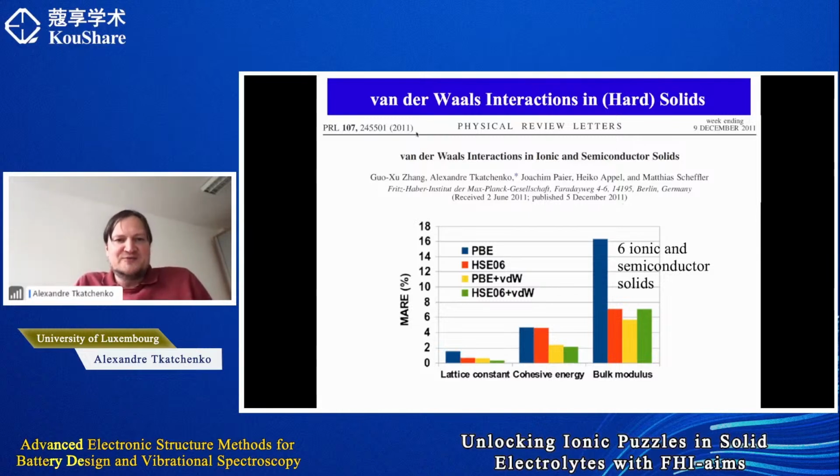I think this is really the first work together with my former student, Guo-Xu Zhang, who I hope is also hearing today. We asked the question of, can you really understand how important or not important van der Waals interactions are in ionic and semiconductor solids? And in this paper, we actually demonstrated that if you take PBE or HSE functionals and you add van der Waals dispersion interactions to it, all the cohesive properties, lattice constant, cohesive energy, and bulk modulus actually improve.